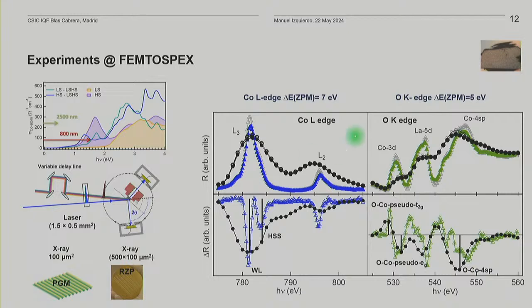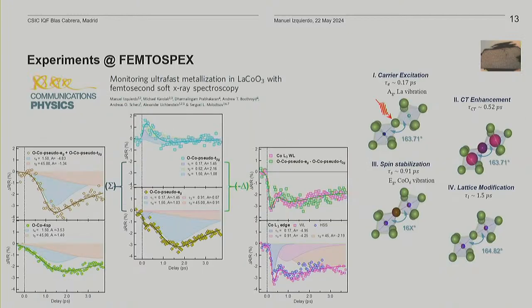So basically, you see the blue gray spectra. This is what happens when you measure the sample with a plain grating, and then the black is when you measure with femtoslicing. The advantage in the second case is that you have a femtosecond resolution. The summary of experiments is as follows.